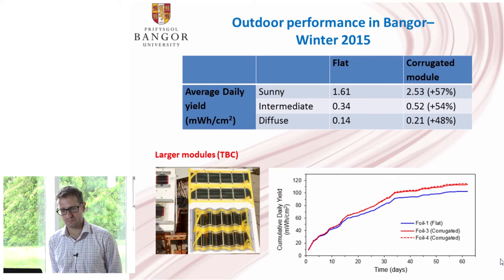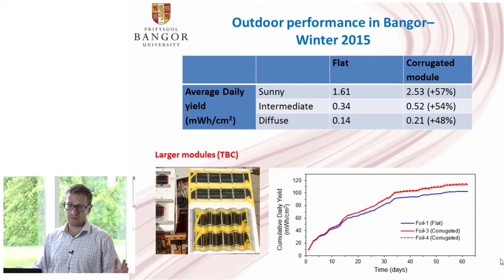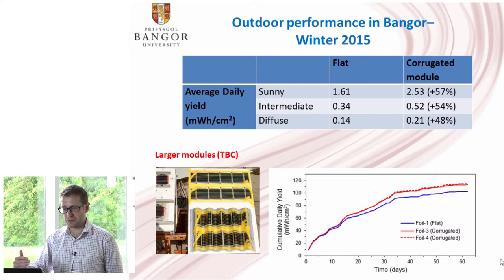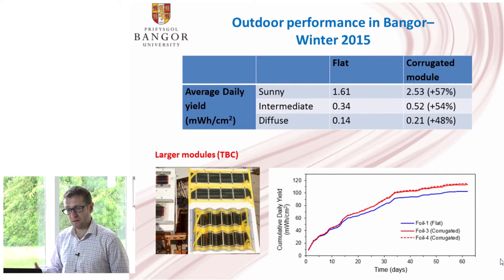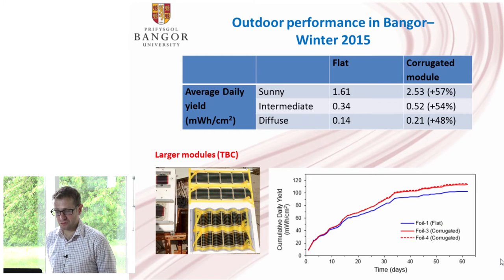And then finally, what we've been looking at is larger modules. So going towards these, I think they're around about 60 centimeter wide modules, which we test, and we can compare corrugated through to flat modules. And if we look at the total yield of these modules, what we tend to find is that our corrugated modules outperform our flat modules by quite a significant amount.